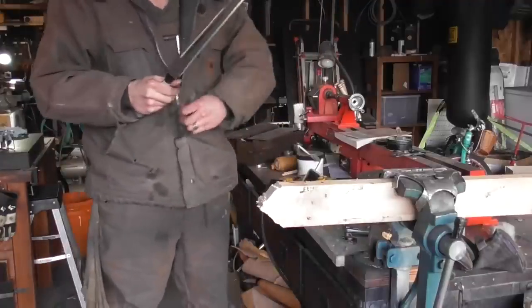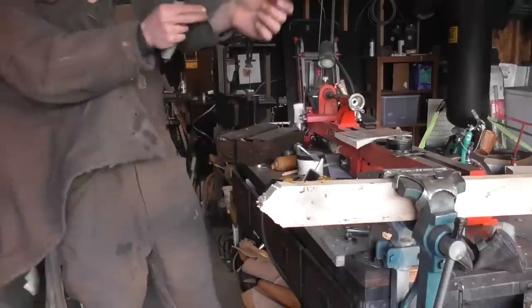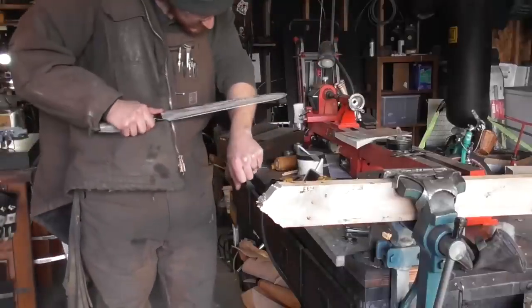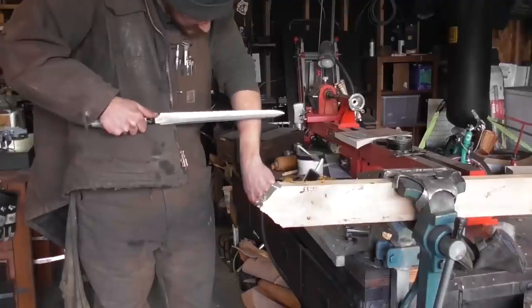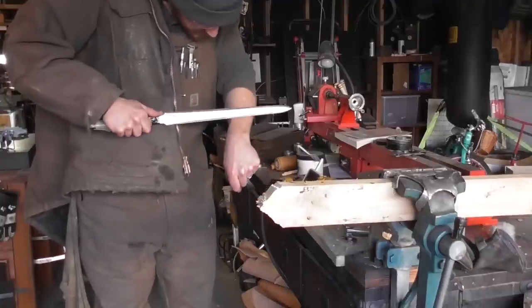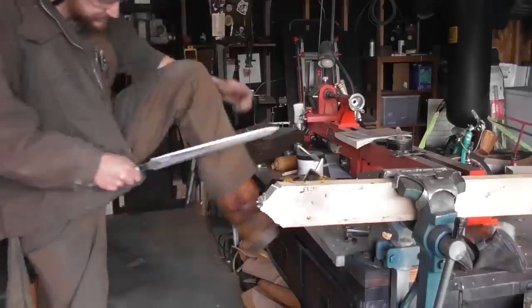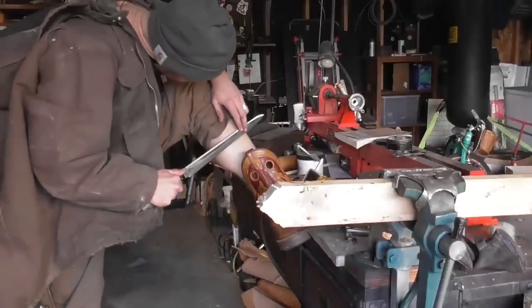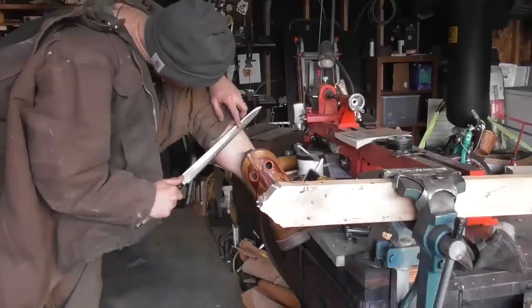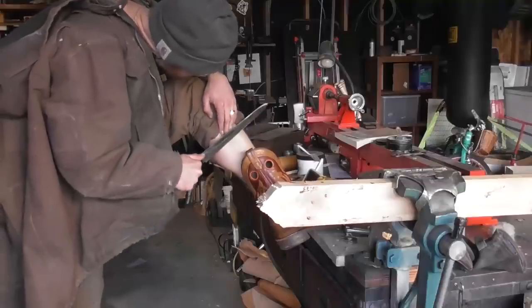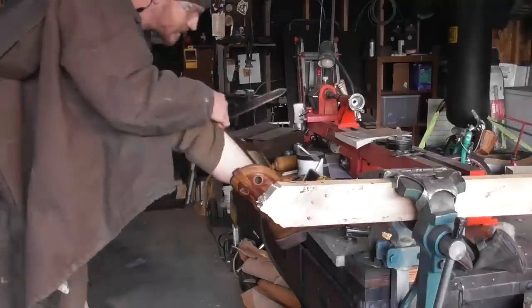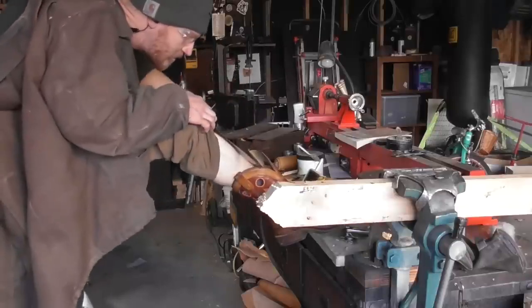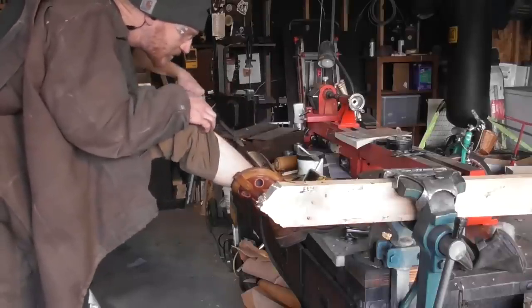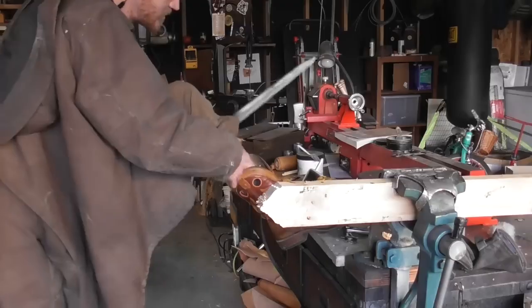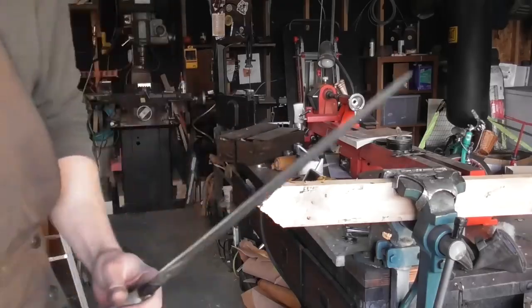Okay, the moment of truth. Will it still shave? Now, it was pretty cold out when I was making this, so I was wearing my jacket. And here I'm testing that area of the blade that I was focusing the chopping on, and it is still shaving sharp. So I will count that as a successful blade. Don't need to go back and reheat treat it. If I did need to reheat treat it, then I would probably need to grind the edge back a little bit. Not a lot, but just to get that thickness to where it's not going to cause any problems with the heat treating. And then I would have to retemper it and re-put an edge on it and go through the testing process again.